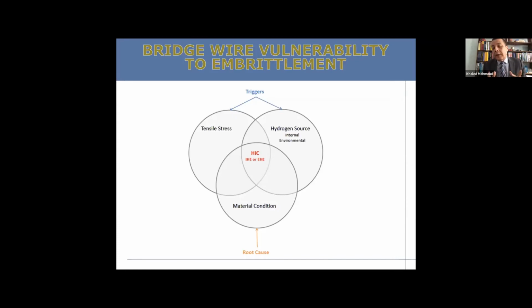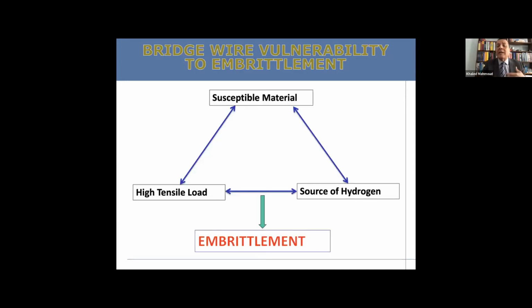But the vulnerability to hydrogen embrittlement comes about because the distance between the grains gets increased when you elongate the grains, and that introduces atomic hydrogen. And then you have that triad of tensile stress, hydrogen source, that's the internal environment of the cable, and actually you get hydrogen in the lattice of the wire material during the galvanization of the wire. And then you have the material condition that is the root cause, and then you have the hydrogen-induced cracking, or what we call hydrogen embrittlement. So that susceptible material coupled with the source of hydrogen and the high tensile load, and you end up with